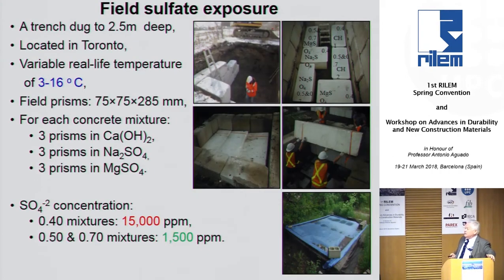And we also did a field site. We don't have sulfate soils in Toronto, so we decided to create an underground site in tanks that would allow us to simulate the temperatures that occur in foundations, where we might have cool temperature attack. And again, we did various concentrations, and the one we picked was 15,000 milligrams per liter, or 15 grams per liter of sulfate, which represents the condition in Western Canada, sort of the worst case condition. And we would require 0.4 water binder ratio for those situations.